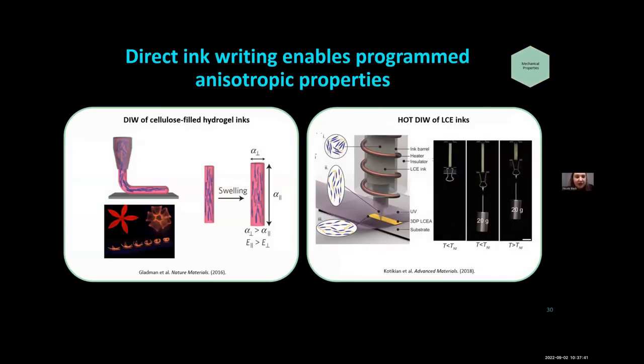And so we didn't just want to create this nice architecture with 3D printing. We wanted it to have a functional value. And so in Jennifer's lab, there have been several grad students who've been doing very interesting work with programming anisotropy into materials via this extrusion-based 3D printing. So on the left is a paper from Sydney Gladman, where she was creating these hydrogel shape-changing flowers, whereby she had a hydrogel ink system and included these cellulose nanofibrils in it, that due to these high shear stresses in the nozzle would actually align with the print path. So essentially these filaments would differentially swell depending on where these cellulose fibrils were sitting, and you could create these cool shape-changing architectures.